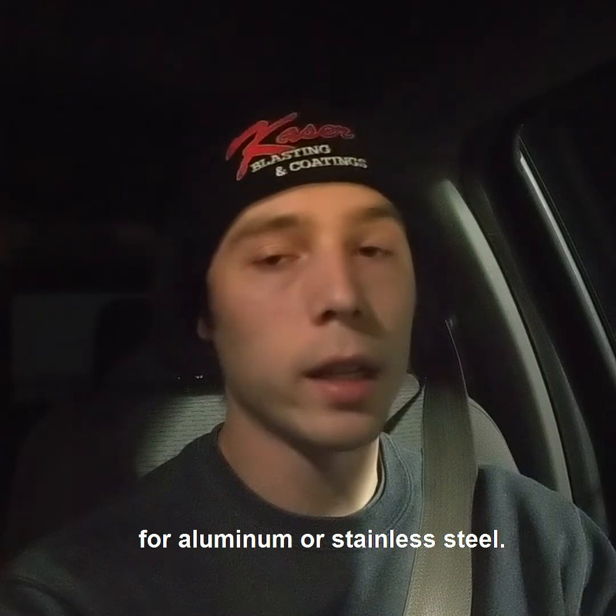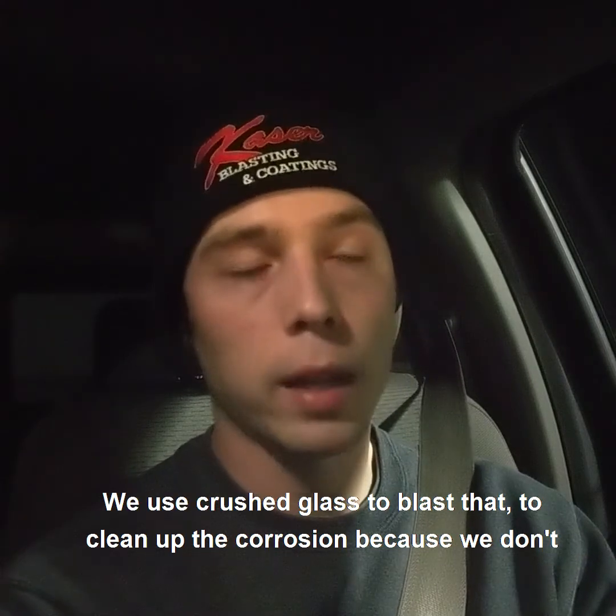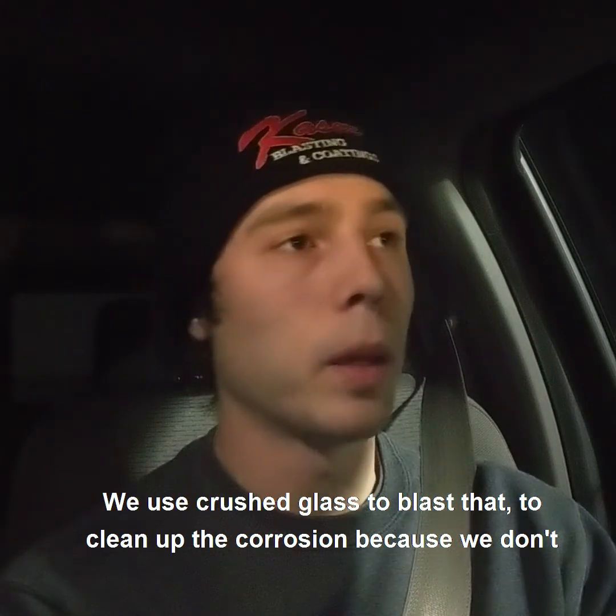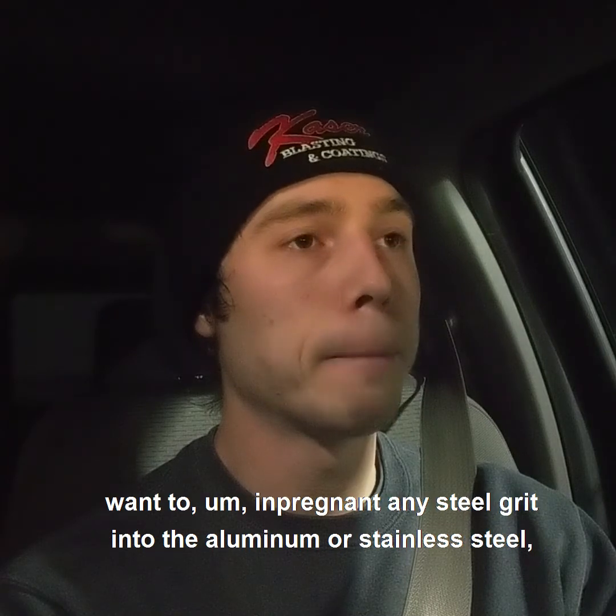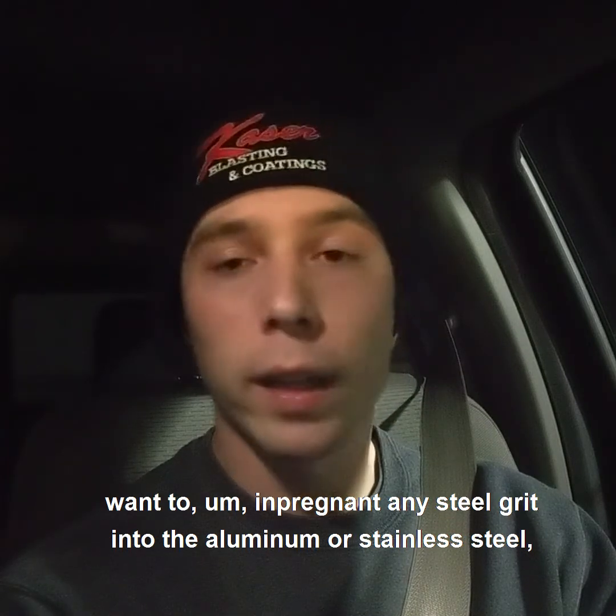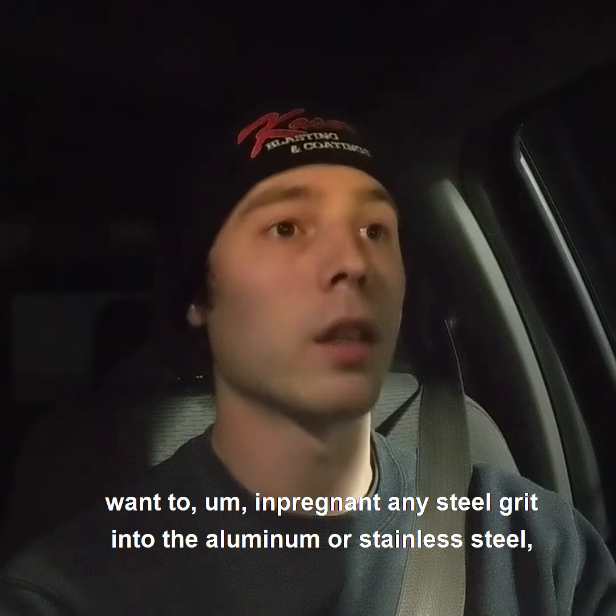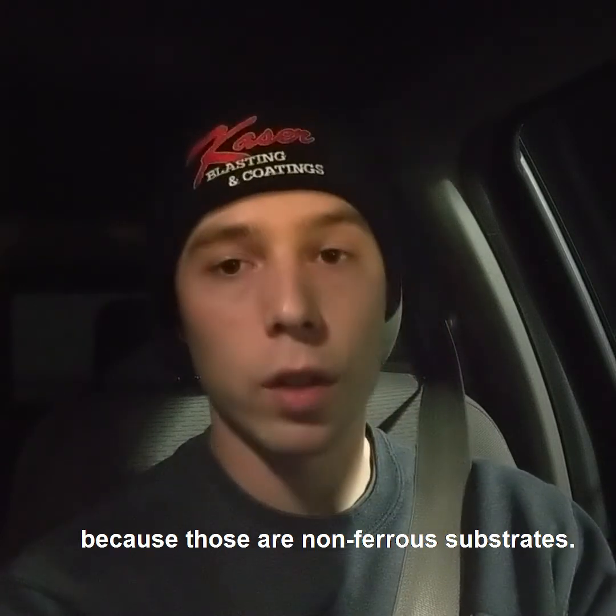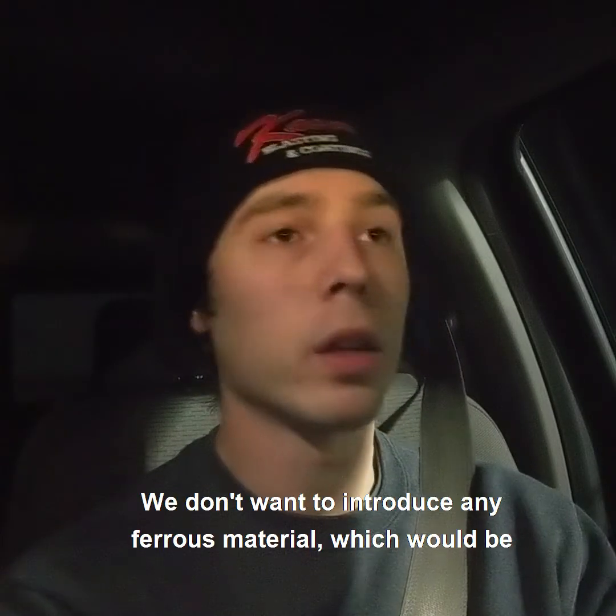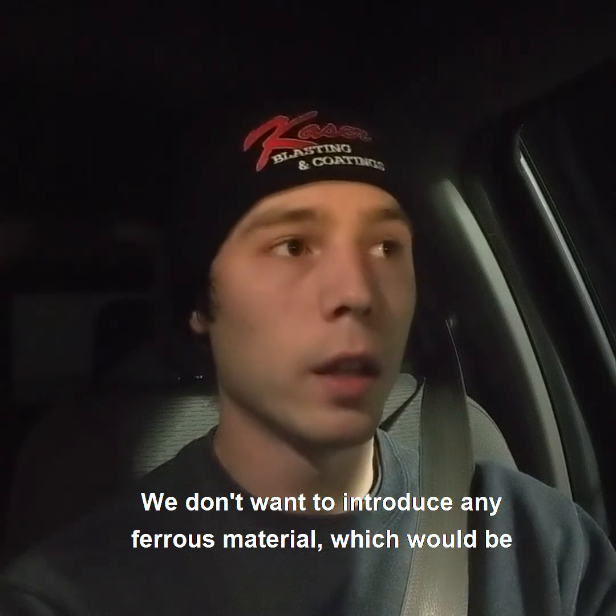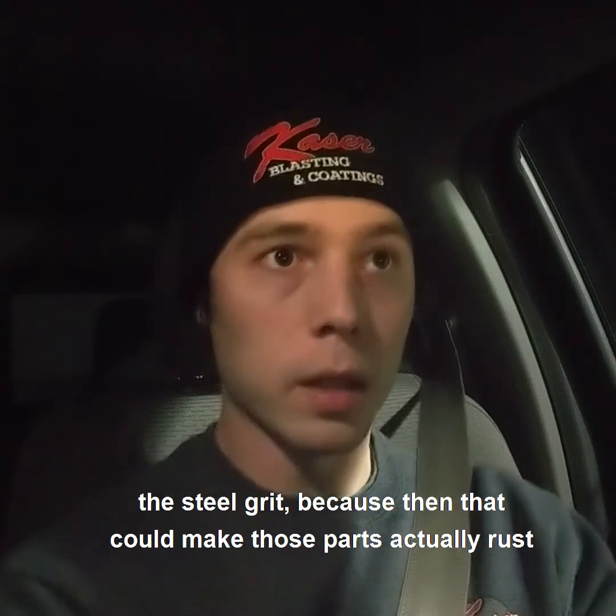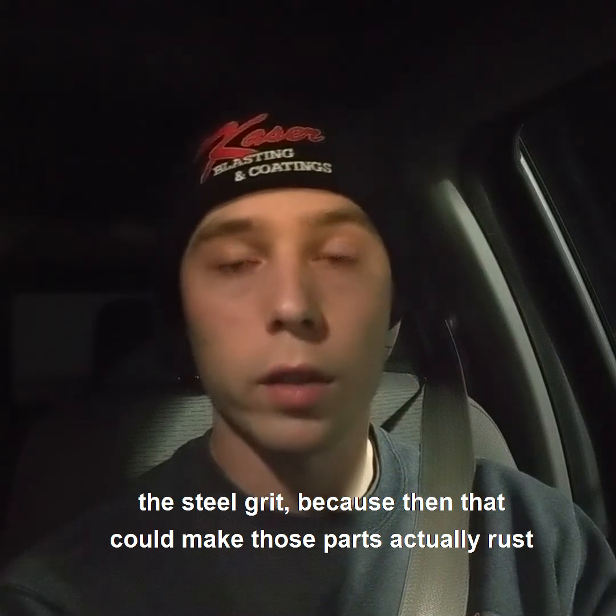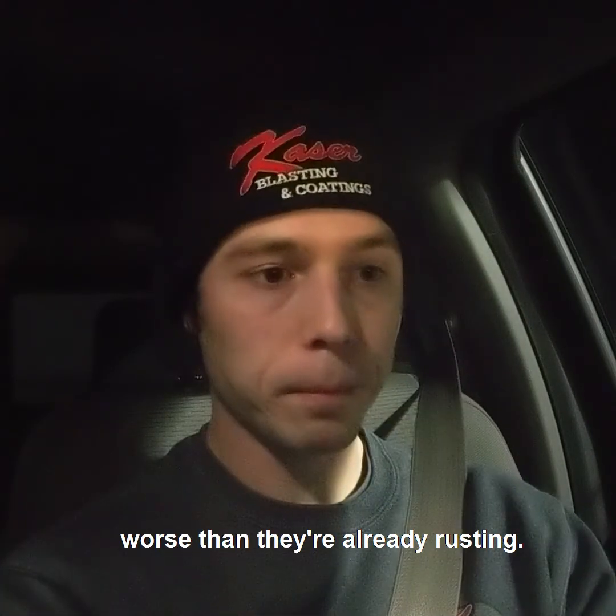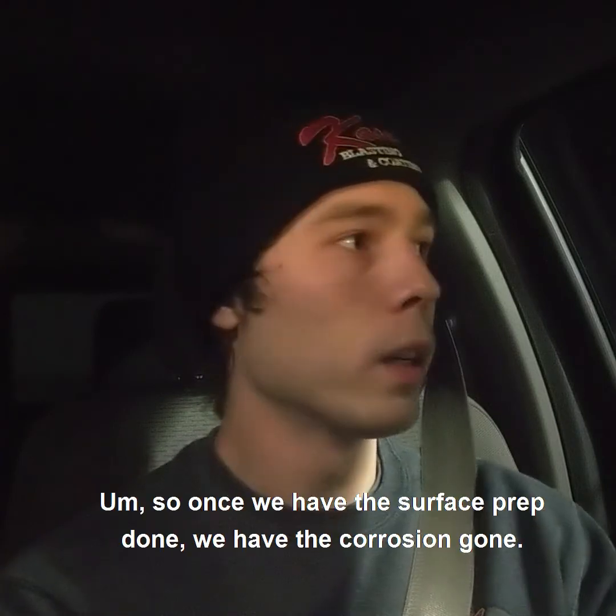For aluminum or stainless steel, we use crushed glass to blast that, to clean up the corrosion, because we don't want to impregnate any steel grit into the aluminum or stainless steel, because those are non-ferrous substrates. We don't want to introduce any ferrous material, which would be the steel grit, because then that could make those parts actually rust worse than they're already rusting.